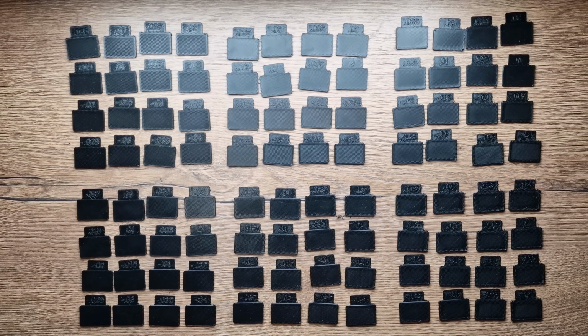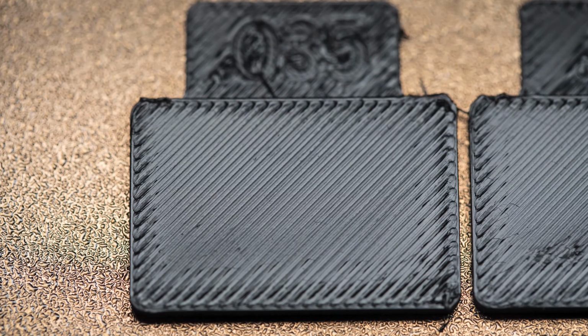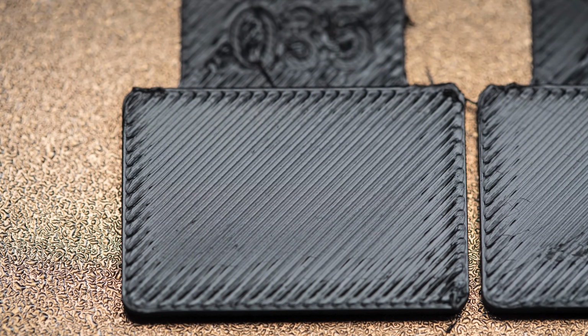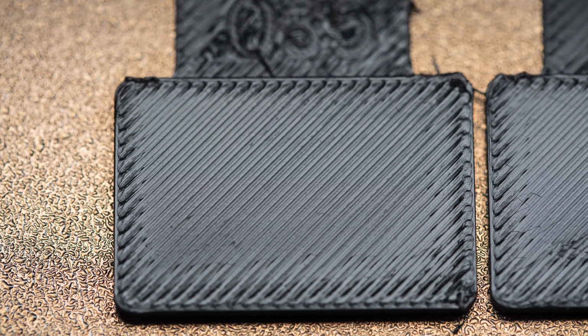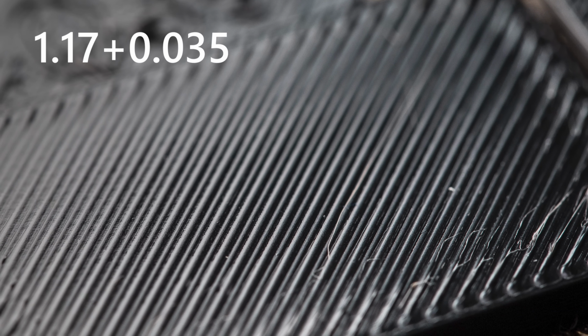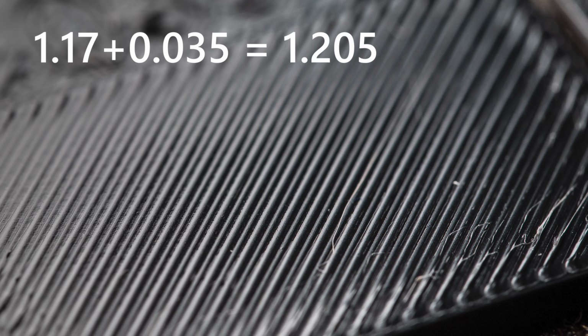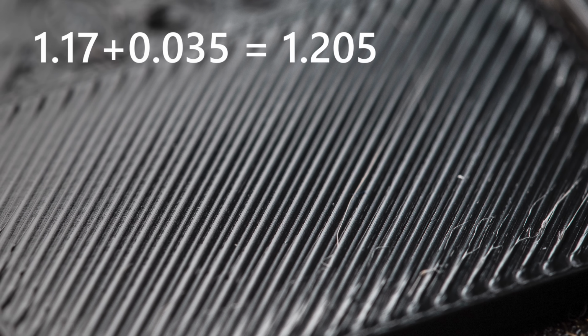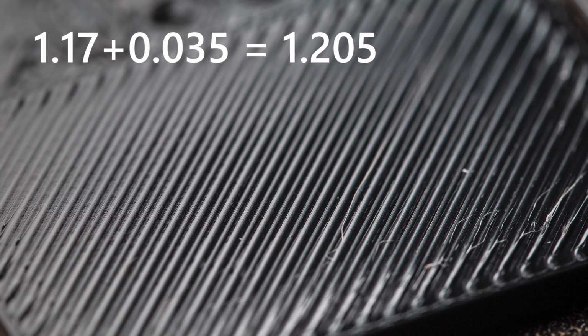Now let's examine the results. Here's the sample from the last print with a correction value of plus 0.035. That means the flow rate here is 1.17 plus 0.035 equals 1.205. I can see the first sign of slight overextrusion.